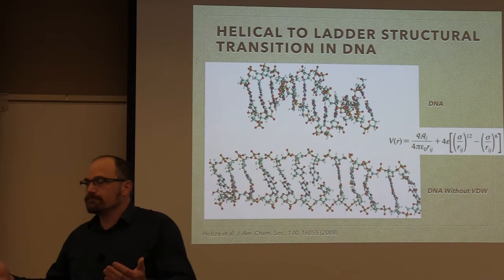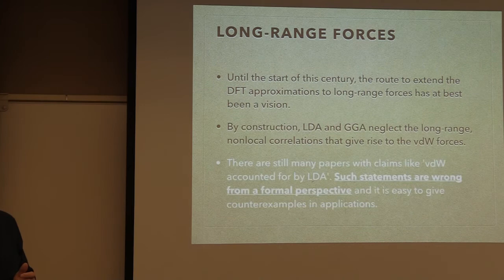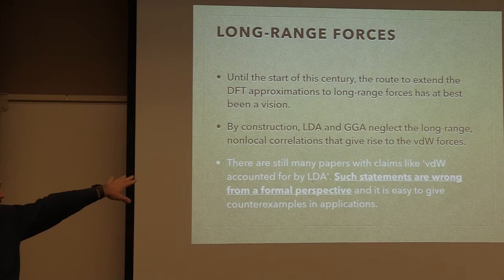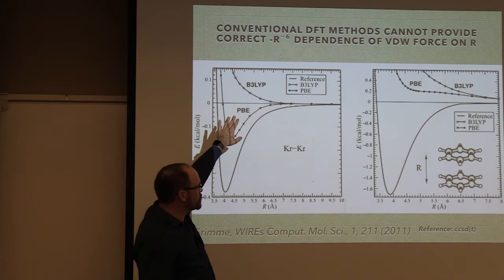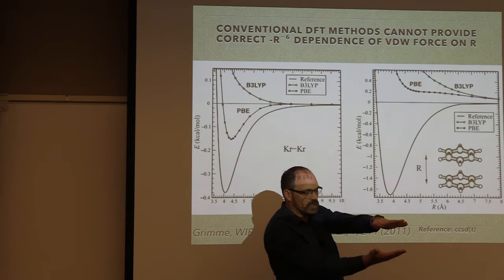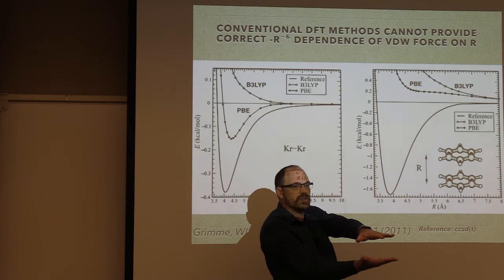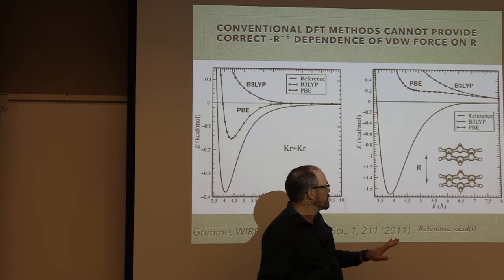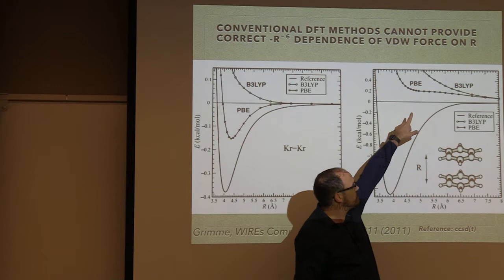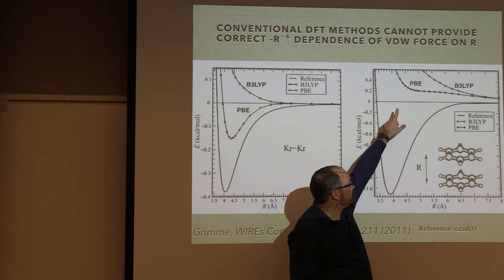LDA that's not correct, of course. For two benzene molecules, they will actually have pi stacking — there's a Van der Waals attraction between them, and they will be about 3.8 Ångströms apart; that's a fact. Well, if you use B3LYP, which is supposed to be this wonderful hybrid functional, it completely misses it — there is not even a minimum; the minimum is at infinity, meaning they separate. PBE is the same — it will not include that attraction. This is the simplest example you can think of, and yet you get it wrong.